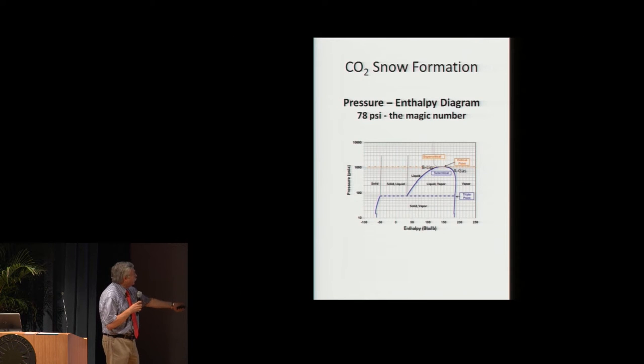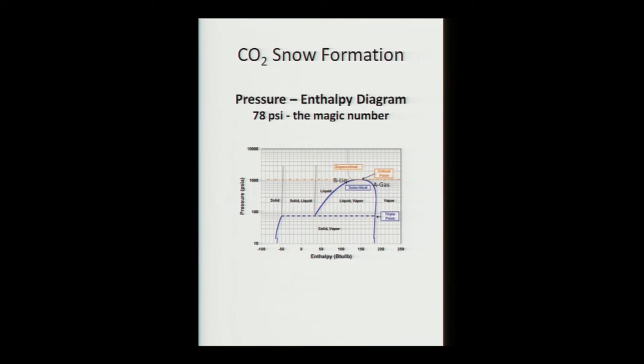Essentially with liquid, we're boiling the liquid, generating gas bubbles in the nozzle. As the pressure falls in the two-phase region, you hit what I call the magic number, 78 psi, and whatever liquid was left in the nozzle becomes a solid phase. So as the pressure drops, you're forming a solid, and then that solid is accelerated to the surface where it hits the surface. With a CO2 gas feed, if you have what's called an adiabatic nozzle, you go down the same straight line, which is a constant enthalpy expansion, and you hit the magic number, 78 psi, you get about 6% CO2 snow as compared to about 42% when you use liquid CO2 feed.